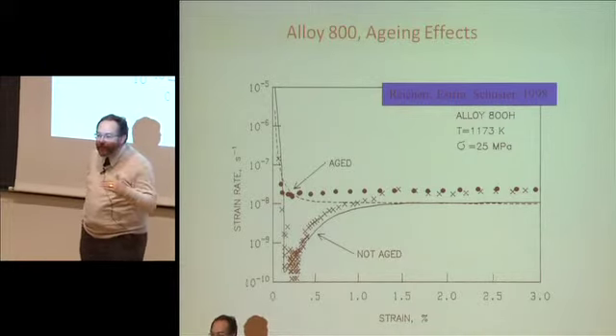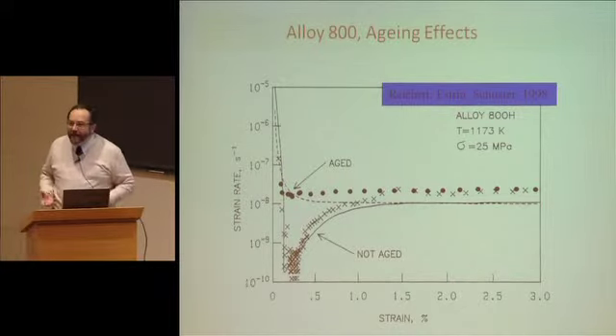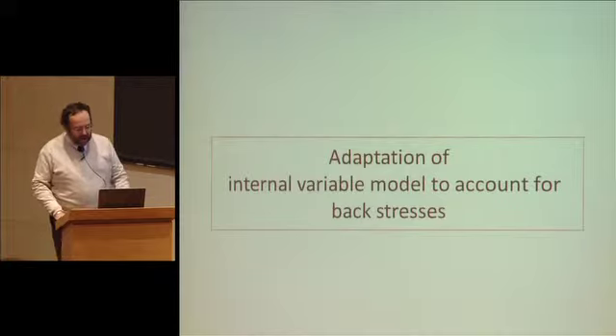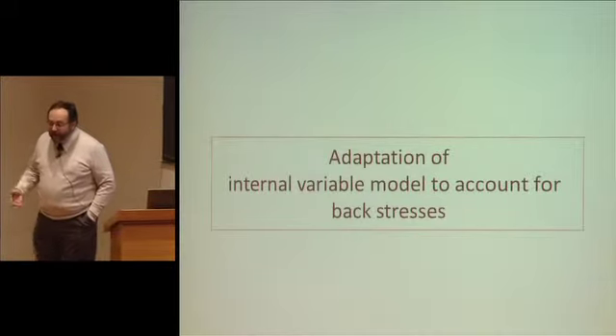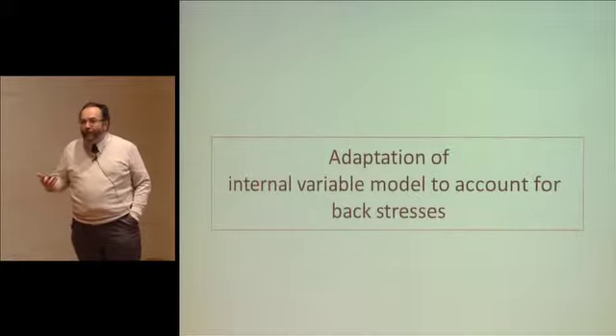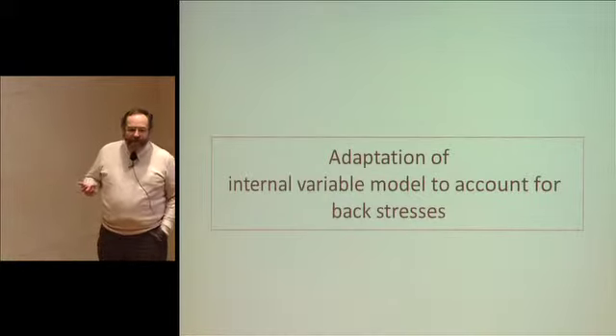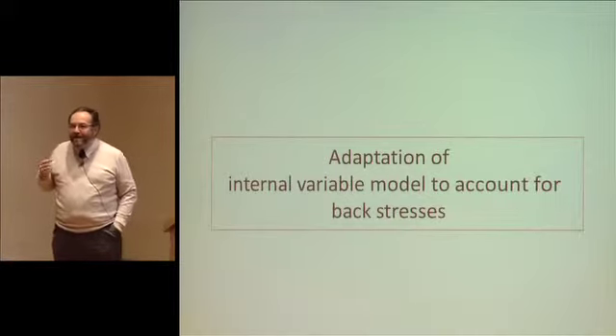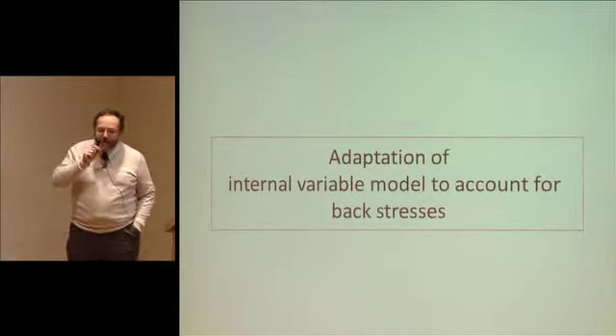You have the experimental points here, little crosses, and you have the forecast behavior with experimental points that takes the evolution in the microstructure into account. If you have precipitation kinetics here and then coalescence kinetics. So typically this is what you can do in some instances where you can reasonably disconnect microstructural evolution. It's not always the case, but in some cases it is. So if you now want to discuss polycrystalline materials with variable textures, you need to get back to basics.